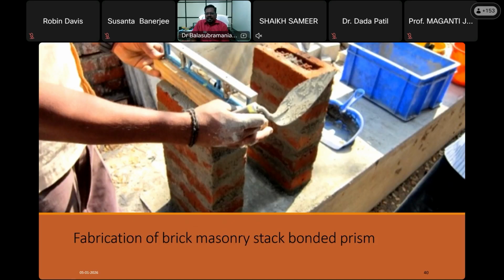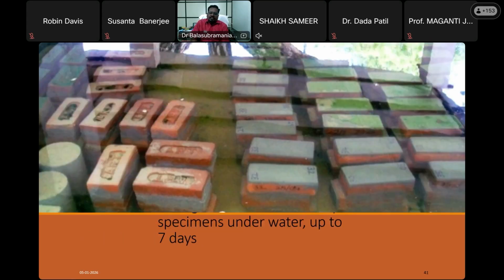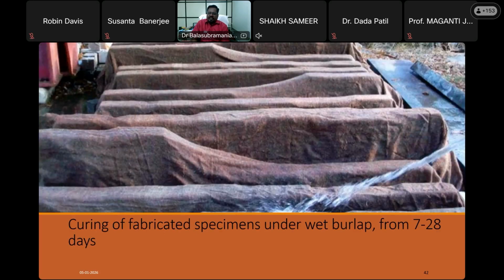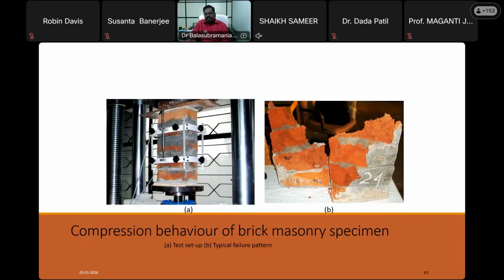This is the standard brick masonry prism. How to fabricate, right? I showed you that at every level the horizontalness has to be ensured. So this is the first stage of curing that we carried out, and then the second phase after 1 week, we used gunny bags for curing. And this is the compressive stress strain relation for masonry test. The standard prisms were subjected to monotonically increasing displacement. We used a displacement control machine, and then we obtained the stress strain relation.